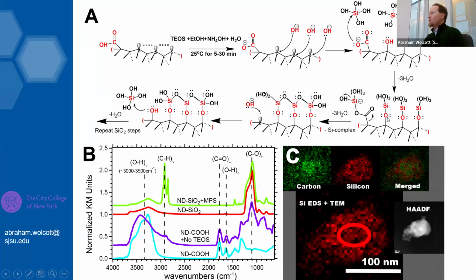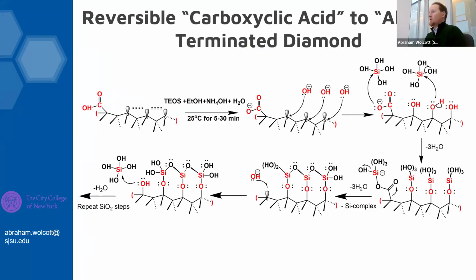Again, you leave the water, you create your carbon-oxygen-silicon bond, and you continue on with your chemistry, and the growth proceeds. What's interesting is our carboxylic acids end up becoming lost during the silica chemistry, and that can be a discussion for another day. But I think it's very important for us to understand the mechanism for the growth of our silica. And so I think that was one of the reasons that Peter reached out, is that this might have been a key aspect that he wanted to explain in his work.